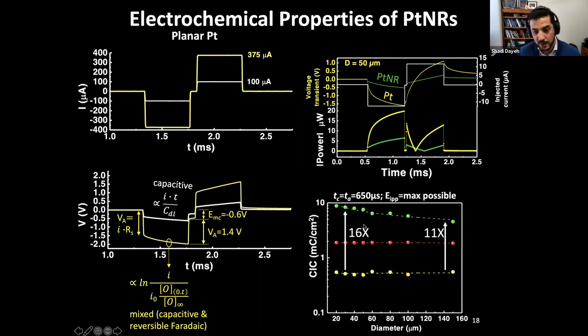And if we do that and we look at the lower right plot for platinum, PEDOT, or platinum nanorods, we can see that platinum nanorods have a relatively higher charge injection capacity, over one order of magnitude higher than planar platinum, and maybe about 6 times or so higher than PEDOT:PSS. And this is good for safety. It's also good for saving power for permanent implants. And that's what the top plot tells us.